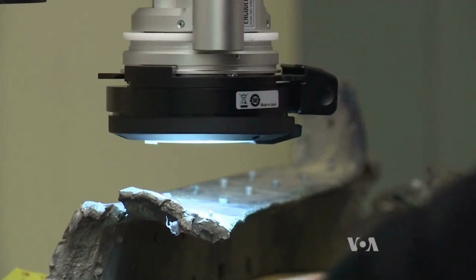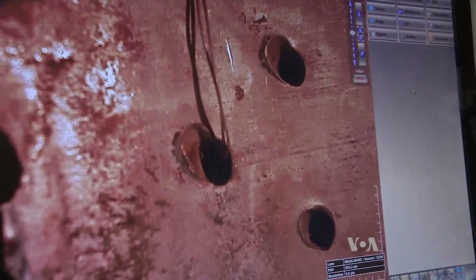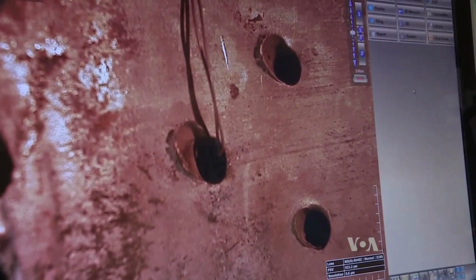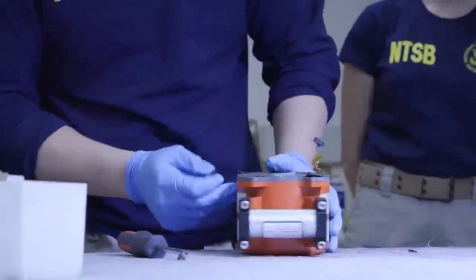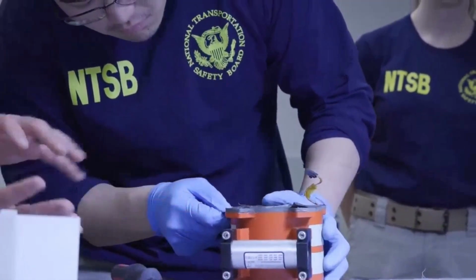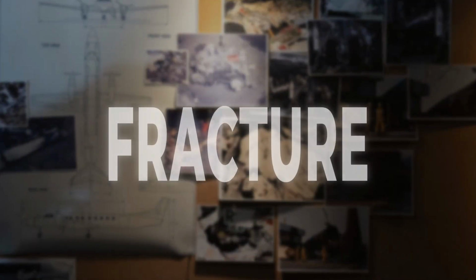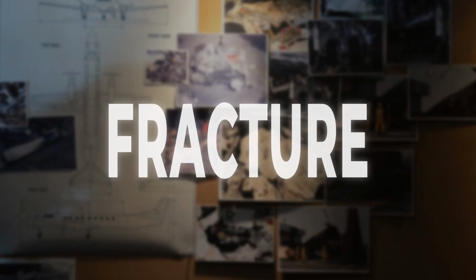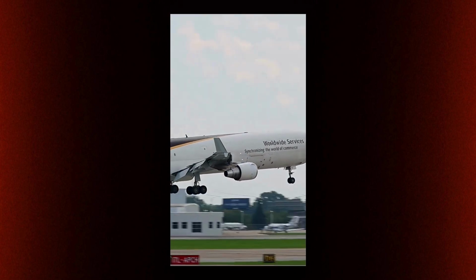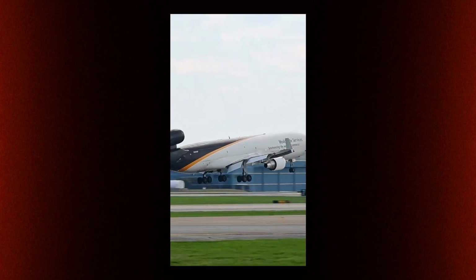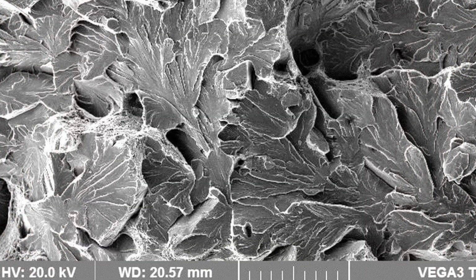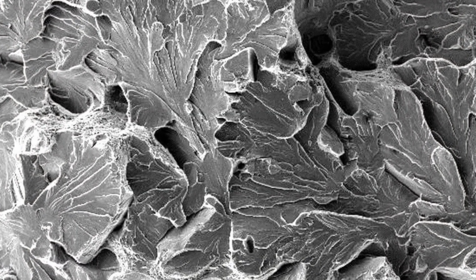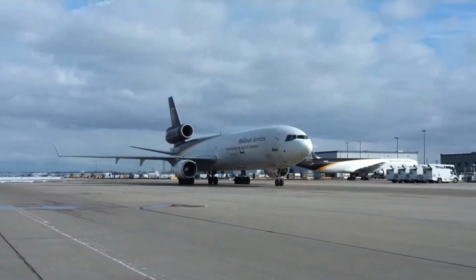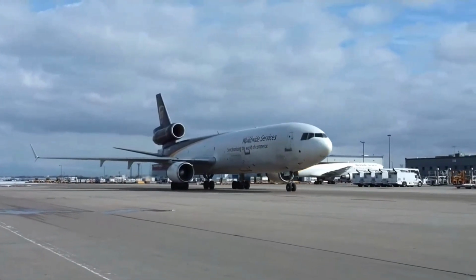Every anomaly found in the lab, every deviation in geometry, hardness, or chemistry, was logged, photographed, and cross-referenced against maintenance records. The evidence pointed to a slow, relentless progression. A crack born in a zone of rework, fed by the stresses of flight and the scars of imperfect repair, growing until the metal could hold no more. The part's history, written in microscopic detail, would soon raise questions about every similar fitting still flying.